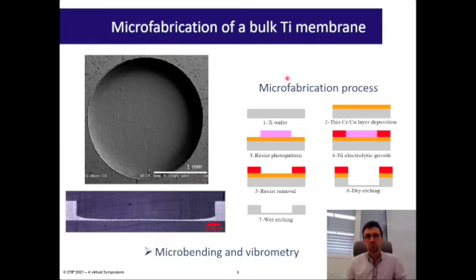And that's how we managed to fabricate them. It all starts with a titanium wafer. Then you deposit a thin chromium-copper layer by thin film deposition. You pattern some photoresist on it to use it to perform a step of electrolytic growth to create a nickel hard mask. Then you remove this photoresist, and you can finally use the step of deep reactive ion etching. Finally, you use a wet etching step to remove the nickel hard mask.